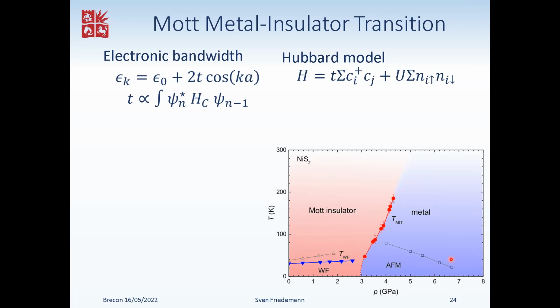Mostly this is inferred from the analog phase diagram of nickel selenium sulfur, where part of the sulfur was replaced with selenium. Now you'd think that would go the wrong way because it's larger molecules, but actually it increases the overlap of the sulfur dimers. By putting in selenium, you increase the overlap, and hence you do the similar bandwidth control that we're doing with pressure. And their magnetism has been observed as well and been studied with neutron diffraction and of course with magnetic bulk probes. And that's how the magnetism was established in the first place. And then in resistance, antiferromagnet signatures have been observed at high pressures and have been interpreted as the antiferromagnetism, including a peak of the A coefficient as you come close to this 7 GPa.